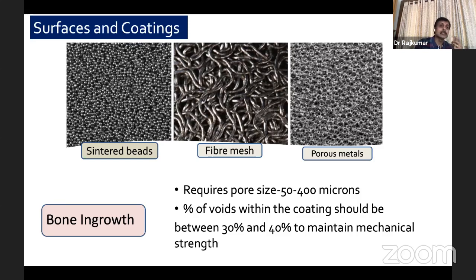Apart from that, the engineering, that is the surface coating and the implant metal itself, helps. It helps in two ways: either the bone ingrows or overgrows. The bone grows into the coating, like in sintered beads or a fiber mesh or porous metals. Nowadays, a lot of implants are porous metals, so the bone grows into that porous material. It requires a pore size of 50 to 400 microns. The more the porosity, the more the bone ingrowth.